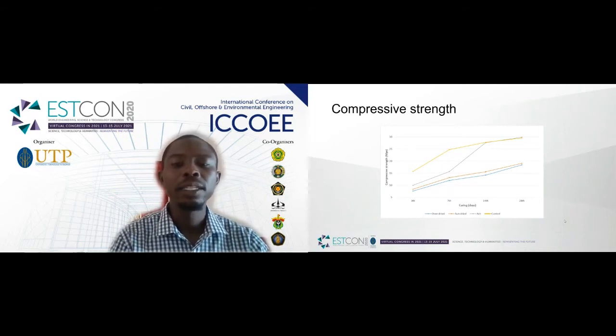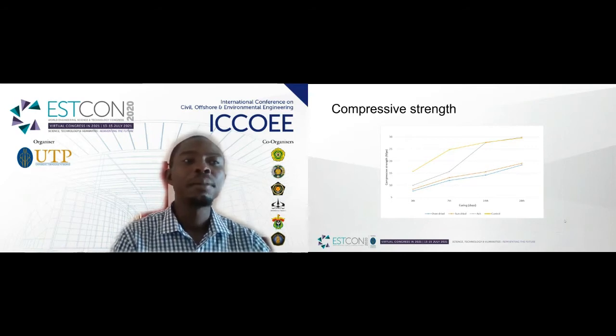From the graph, compressive strength development at 3, 7, 14, and 28 days of curing is shown. Considerable increase of strength occurred after the curing period was completed. The mortar strength obtained from the average of 3 specimens at 15% replacement level, the seaweed, the compressive strength developed at 28 days is 29.9 megapascal, which is slightly higher than the control mortar, 29.6 megapascal.